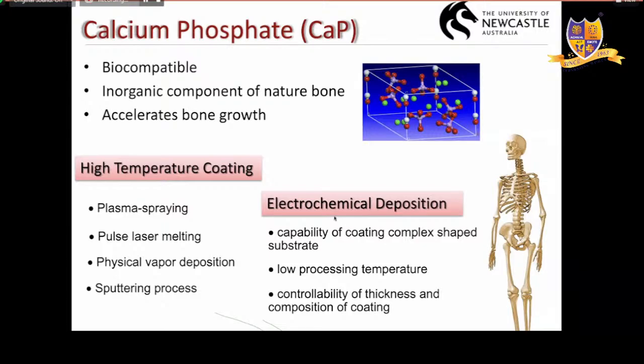And there are advantages. You can coat complex shapes, which is very important, right? Because your implants are of irregular shape. You also have a low processing temperature. You can control the thickness by altering the voltages, current, and also tailoring the electrolyte of the coating solution. And it's quite simple and inexpensive.